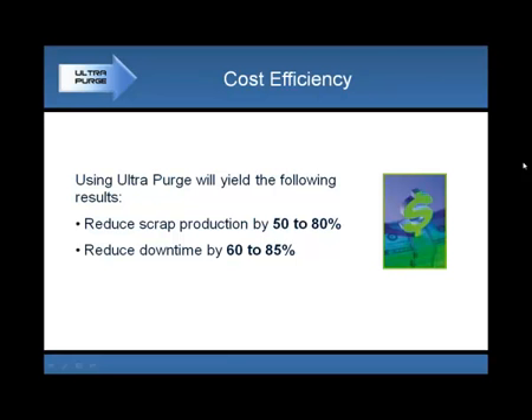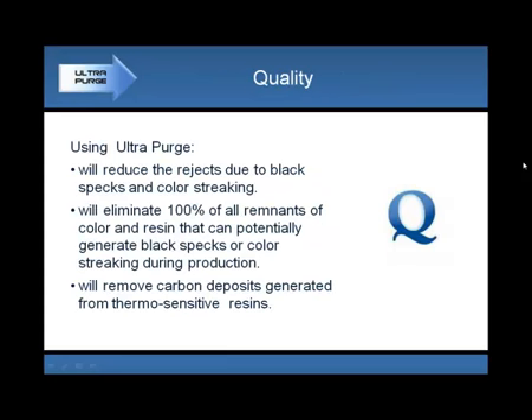It really depends on the setup of the machine, on the polymer, on the colorant, on the type of hot runner. So sometimes we can achieve very high savings, very close to 80%, sometimes even 90%. But sometimes we cannot because of the design of the machine or the type of current, and we are down to 50%. But definitely consider 50% as a very conservative number. It is always correct. So using UltraPurge can always save at least 50% in reduction of scrap or definitely in downtime.